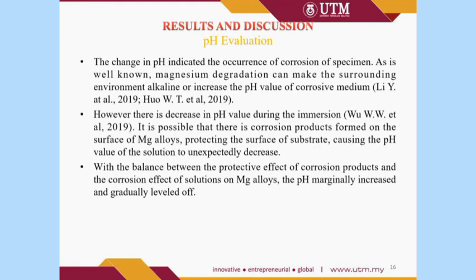The change in pH indicates the occurrence of corrosion of the specimen. As we know, magnesium degradation will make the surrounding more alkaline, or increase the pH value. However, there is a decrease in pH value during immersion. This is probably due to the corrosion product formed on the surface, protecting the surface of the substrate, causing the pH to reduce. With the balance between the protective effect of the corrosion product and the corrosion effect of the solution on magnesium alloys, the pH marginally increased and gradually leveled off. Although there was a fluctuation in the pH value of the corrosive medium, it is overall considered that the pH value of the corrosive medium increased, indicating that corrosion occurs.